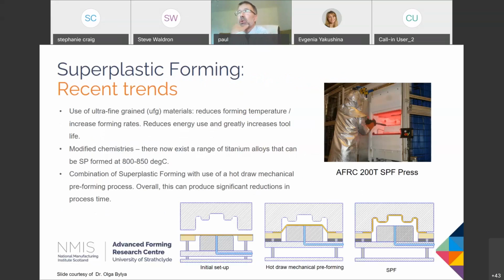So one of the things we said we'd talk about was what's going on in the world of superplastic forming, what are the recent trends. And the top two really relate to titanium alloys that are probably the most difficult materials to form using superplastic forming in some senses. There's a big push over the last few years to look at the use of ultrafine grain materials. So these are classically Ti-64 that's been processed using very careful rolling procedures to actually generate a grain size of less than 1 micron, so very fine indeed.